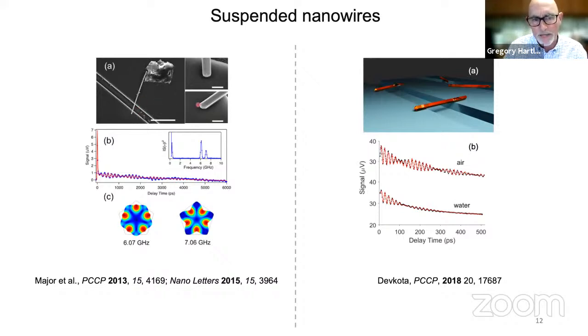So the experiment on the left is for a very large structure, and we did this so that we could measure the dimensions of the structure by SEM. That's what it looks like. It's a pentagonal structure, sort of typical with gold nanorods that you make by chemical means. For a pentagonal structure, you get two breathing modes, one where you have basically motion at the apexes of the structure, and another one where you have motion at the faces of the structure. They have different frequencies. This is the transient absorption trace, where you clearly see two vibrational modes that are going in and out of phase. We measure the frequencies, and then we can calculate what we expect them to be based on the dimensions we got in the SEM, and we get extremely good match between the measured and calculated vibrational frequency.